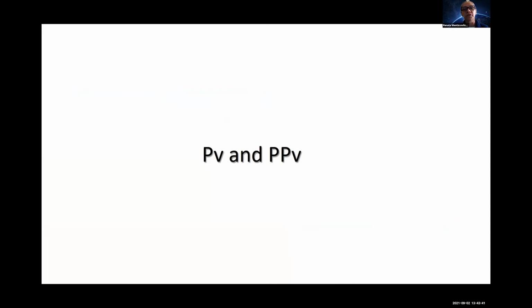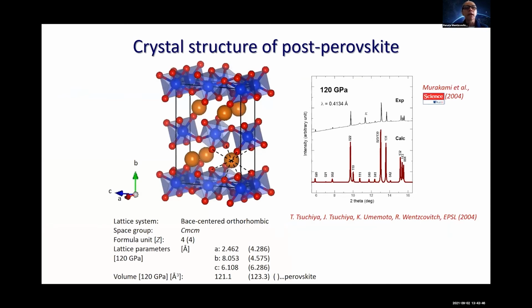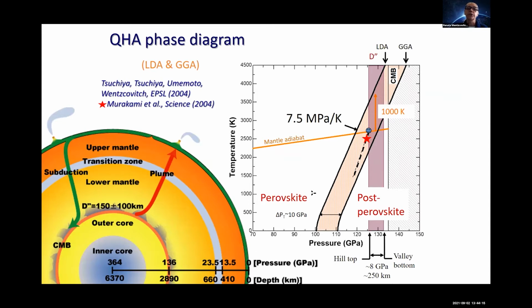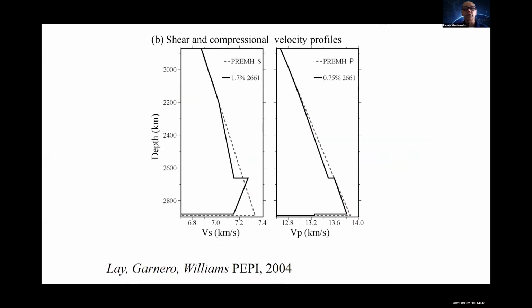Regarding 2004, it was a year that we learned a lot about methods. It's because of the discovery of the post-perovskite transition in a diamond anvil cell at 120 GPa and 2500 Kelvin. We received the X-ray diffraction from Japan and started searching for this phase. By random search, starting from possible crystal structures, we identified this phase that was thermodynamically stable at high pressures and temperatures. And this was the phase boundary that we calculated using different functionals, and it displayed for the first time the accuracy or inaccuracy of DFT in predicting phase boundaries, or differences in energy between phases. This was a remarkable success that pointed right away to the uncertainty of these calculations. Which are still there.